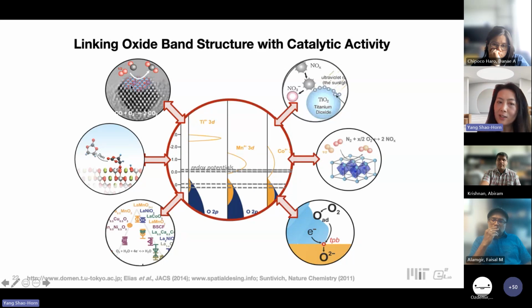Right? CO oxidation also requires a tuning of surface oxygen site in order to optimize the activity, as well as NO oxidation to NO2, right? So removing NO is a really critical challenge in our NOx emission, or for environmental challenges associated with internal combustion engines. And it turned out tuning the metal-oxygen p-band center can influence the development of more active oxygen sites for NO oxidation to NO2.